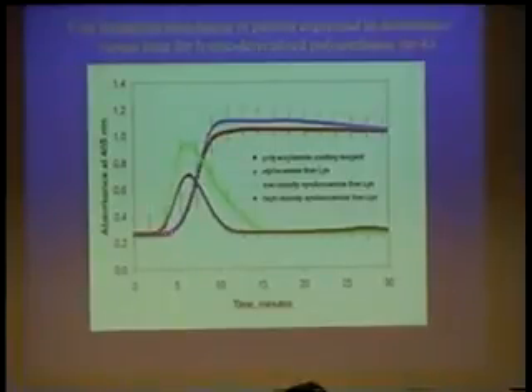In the controls, the absorbance just goes up in an S-shaped curve and levels off and stays constant over time. And the same thing basically happens with the alpha amine lysine, which does not have the epsilon amine group free and therefore has not picked up the plasminogen and the TPA. With the active surface down here, the clot begins to form, but then at a given point in time, not too far into the time scale, the curve turns over and comes back down again and goes, in fact, all the way to the baseline, showing that the clot, or at least the absorbance, has gone back down again.